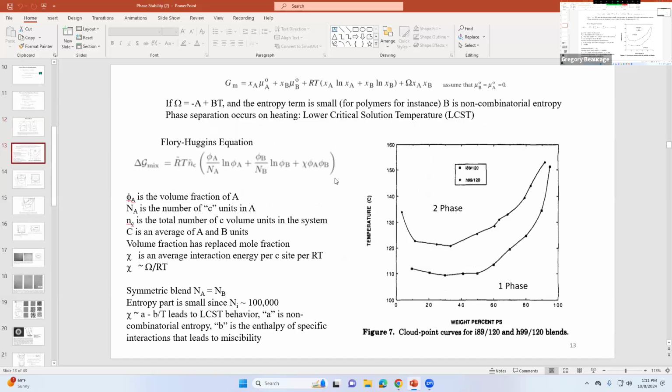Anyway, the difference, though, is that in polymers you have this Flory-Huggins equation. Because the molecular weight is high, the entropy of mixing is really small. Right. So the entropy of mixing goes almost to zero. Then you just have this enthalpy term. So basically it would mean that for a normal case, this usually makes things mix, and this thing makes things demix. So you would never have mixing at all in a polymer because there's no entropic mixing term. So basically this dominates. But there are a few polymers that mix.